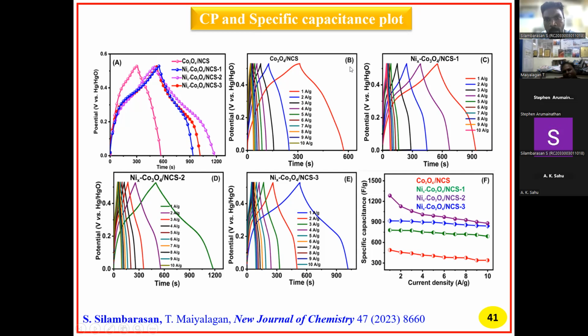Then figure B and figure C, all these figures were measured at around 1 ampere per gram current density up to 10 ampere per gram current density, with an applied potential of 0 to 0.55. So compared to the others, sample 2 has the longer discharge time.